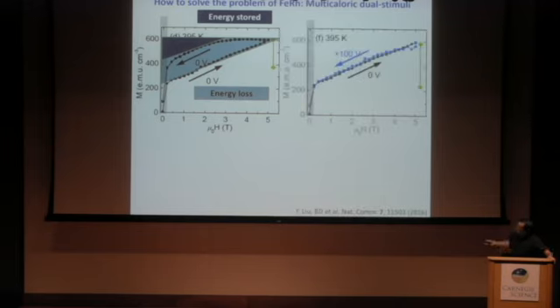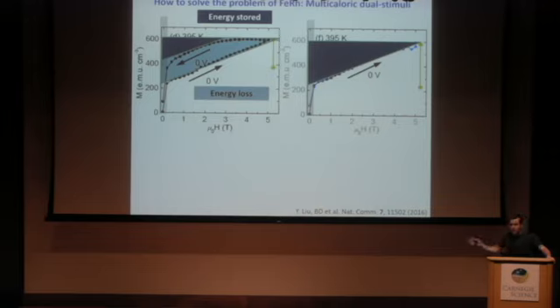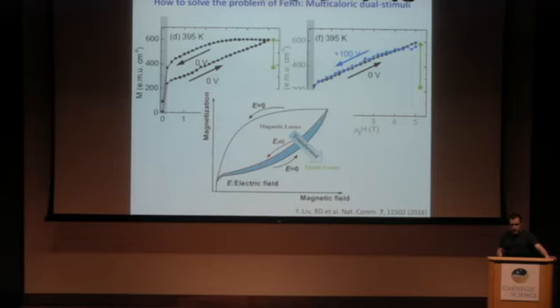Here what we did, we applied the magnetic field. This is the black curve here. And we remove the magnetic field, but at the same time, we apply a voltage on barium titanate. And in that way, we are able to follow more or less, or very close to, this black curve. And now the energy that we have is exactly that one. So we succeeded to remove the hysteresis loop of the magnetic property. Actually, these magnetic losses are not fully lost, of course, because at the interface we also have elasticity which appears. And what we did actually, we just transformed a part of the magnetic losses into elastic losses in that case.